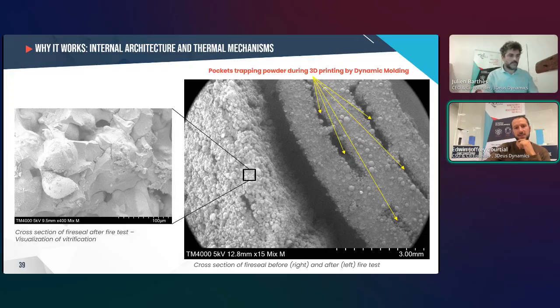They form diphasic regions made of air and solid mineral particles, which provide both deformability and thermal resistance. Now, on the left side, you can see the same material after exposure to the ISO fire test. At this stage, the surface morphology has completely changed.